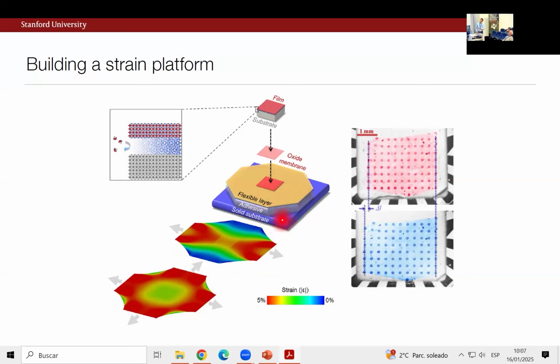So generation one of these sorts of experiments, at least within our group, was to do the following. We have a little crude assembly. We're stretching these things, looking at it under an optical microscope. And the whole thing is sitting on a hot plate. And so we're using a low temperature adhesive that solidifies on the scale of 50 degrees C. And so we literally freeze this thing and then go around and do our measurements.